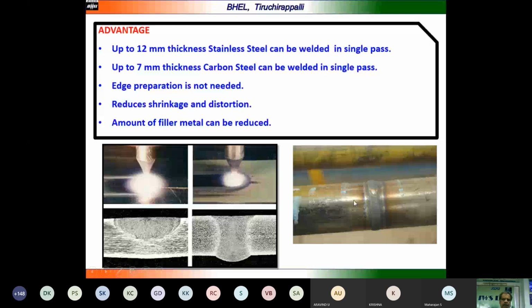You can see the bead width also. The bead width is very small here. And the amount of filler metal consumption and gas consumption also gets reduced. Instead of welding in 3 or 4 passes for a 6 mm or 7 mm tube, you can weld it in a single pass. That means you see a reduction in consumption of gas, consumables, everything.